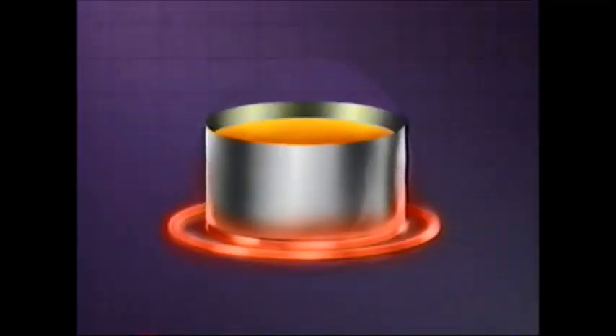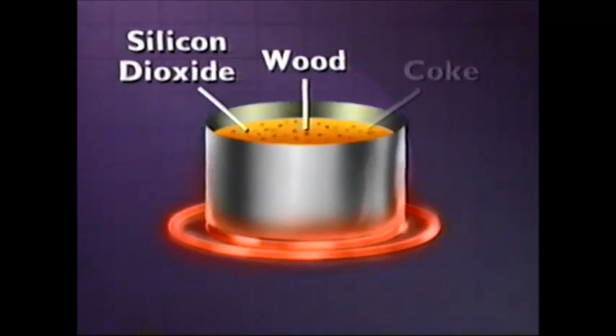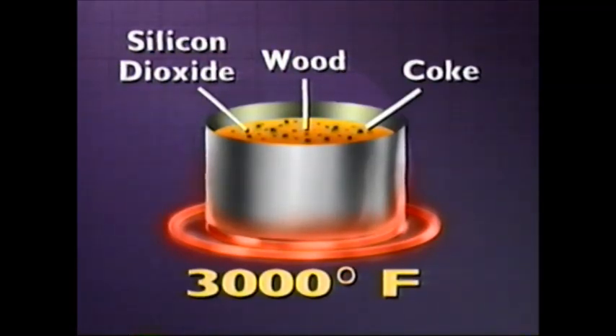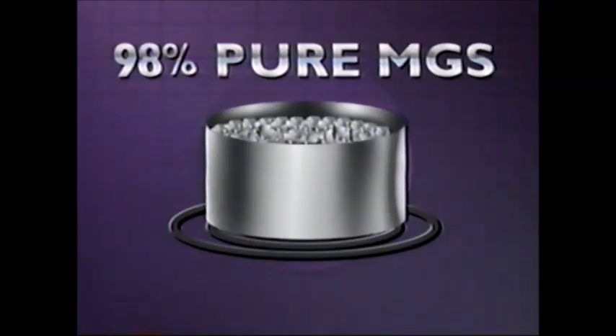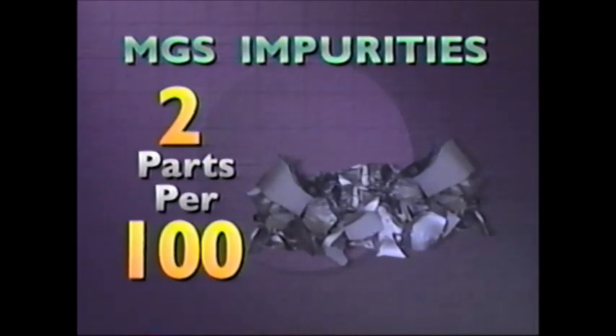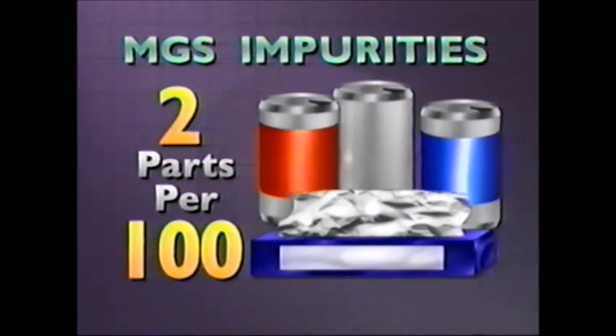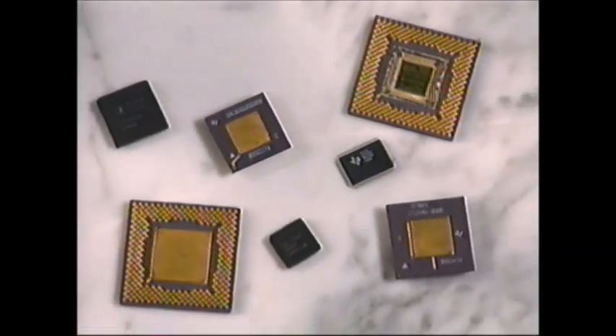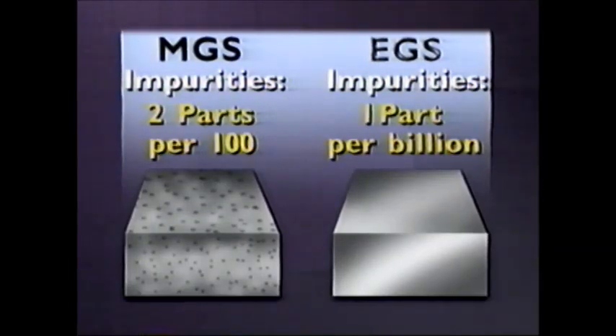It all starts with sand, silicon dioxide, one of the most common minerals on Earth. When silicon dioxide is heated together with wood and coke at over 3,000 degrees Fahrenheit, you get 98% pure metallurgical grade silicon, or MGS. With impurities of 2 parts per 100, MGS is pure enough to make aluminum products such as soda cans, but it's far short of the ultra-high purity needed to make a microchip. For that, MGS must be transformed into EGS, electronic-grade silicon, with impurities of only 1 part per billion.